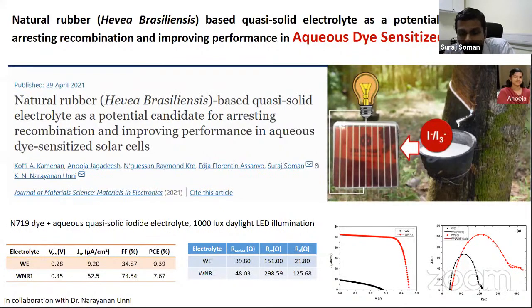Another part is that when we talk about the electrolyte in these devices, we use organic solvents, which are not green, of course, and can't be recycled, and that causes a lot of environmental concerns. One way to address this issue is to transform from organic solvents to aqueous based electrolytes, where we can use water as the solvent. But what we had seen is that the moment you switch from an organic solvent to an aqueous solvent, the conventional additives and other molecules that you add to the system do not perform well. So recently we looked around us and found that we can have certain binders in the form of natural rubber. Here we developed a natural rubber based aqueous printable electrolyte system, and we were able to achieve around 7 to 8% efficiency in indoor light conditions with this new electrolyte, compared to the standard ones, which performed really badly with aqueous based electrolyte systems.